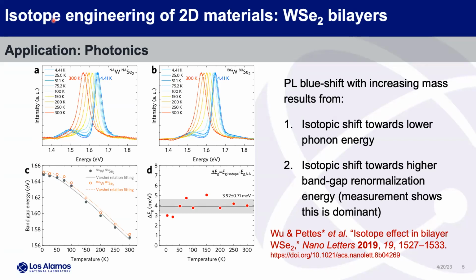But what we didn't expect is the big changes that we saw in the photoluminescence over the entire temperature range from 300 down to 4 Kelvin. This is something we measured with our system. So it's useful for both things, for photoluminescence and for Raman. We measured a 4 millielectron volt shift in the band emission. So this is band gap plus exciton binding energy.